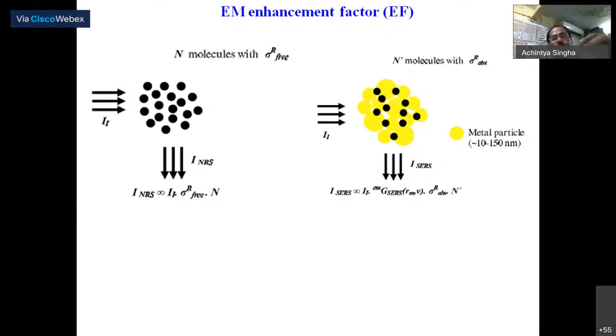But if you add metal nanoparticles, since the nanoparticles have a large surface area, and the molecule adsorbs on the surface of the metal nanoparticle, then what will happen? You can see now some extra term in the intensity, which is the electromagnetic enhancement term, and that term is due to the localized electromagnetic field by the nanoparticle.